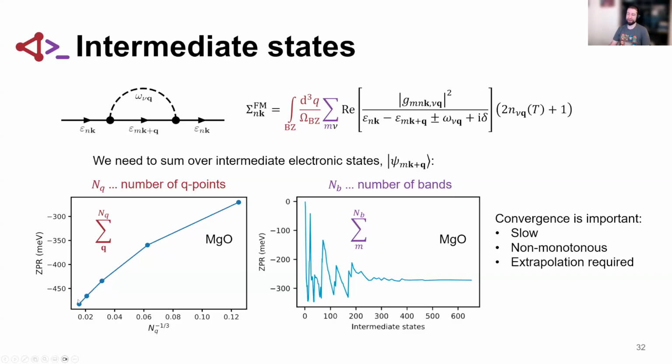And usually the values where you will converge for the materials that I myself tested are somewhere between 32 or 64. I rarely ever had to go beyond 64 by 64 by 64 q points, but it is very material dependent. So make sure that whatever unit cell and whatever material you have, you use the right k points or q-point densities.